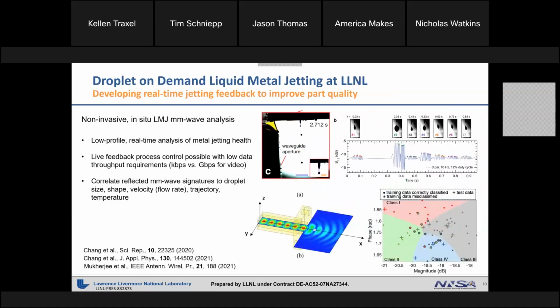So high-speed videography is the gold standard in droplet breakup analysis. However, the high data throughput it demands makes it less practical to provide real-time jetting feedback during a build. Think of doing real-time image processing on gigabits of data per second. In response, we have developed a microwave diagnostic that uses an open waveguide to monitor the characteristics of the liquid metal droplets, as shown in the top left and bottom left figures.